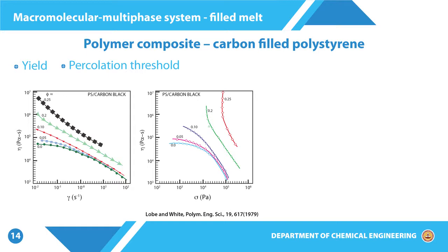What is interesting to observe in such data is also the fact that the extent of shear thinning in, let us say, the 1 to 10 range is almost identical. In other words, the slope of these curves is identical regardless of the volume fraction. So, clearly what we have is most probably identical types and sets of clusters in this range, and given that we just have more of them, the overall viscosity is higher. However, the slope, or the rate at which they change when progressively higher strain rate is applied, is the same.